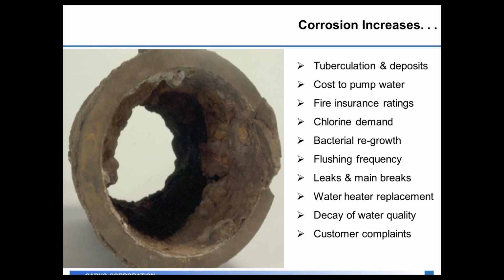Are you seeing an increased cost to pumping water through your pipe? As that pipe gets restricted with scale and tuberculation, it costs you more in energy to pump the same amount of water through the pipe when that scale and tuberculation builds up. Do you have an increased chlorine demand in your distribution system? You're feeding your chlorine at the plant. Do you have to boost it out in the distribution system to maintain that residual in the system? Do you have places where the residual drops off frequently? Those are all good hallmarks that you might have issues with corrosion in that part of the distribution system.